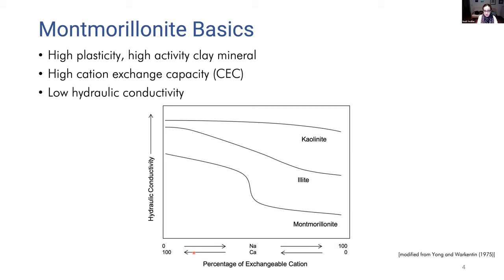As the amount of calcium decreases, the hydraulic conductivity also decreases. In terms of the hydraulic conductivity for typical geosynthetic clay liner materials, we're looking at numbers on the order of 10 to the minus 9 centimeters per second. This axis here, you can think of it as a log scale axis, and changes in the percentage of exchangeable cations would result in potentially orders of magnitude of change in the hydraulic conductivity of the montmorillonite.